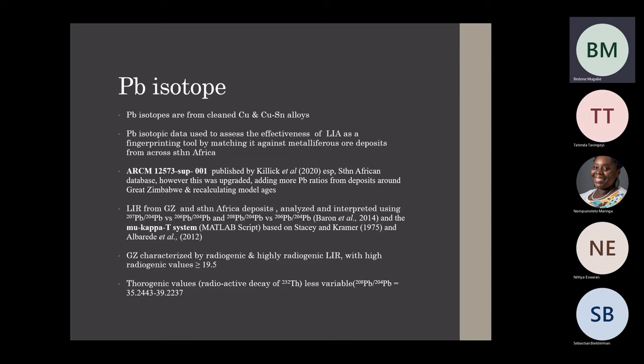So what I realized from the lead isotopic characterization results was that Great Zimbabwe was characterized by radiogenic and highly radiogenic lead isotopic ratios. When we say radiogenic or highly radiogenic lead isotopic ratios, they are characterized by ratios greater than 19.5 on most of the uranogenic plots, while the thorogenic values were characterized by less variability, that's 35.24 to 39.22. Next slide, please.